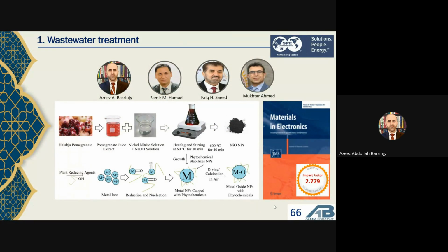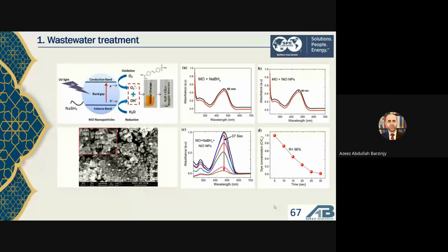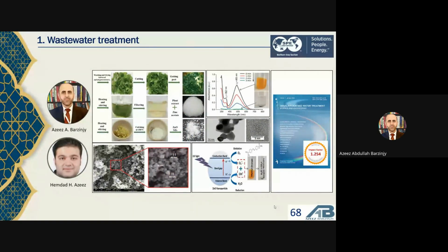And here we utilized homemade Halabja pomegranate in order to produce nickel oxide nanoparticles, again for dye degradation. But in this process, we could decrease the time of the degradation from 60 minutes to only 37 seconds by using the green synthesized nanoparticles. And we also utilized different types of plant extract in order to produce zinc oxide nanoparticles, and also utilized these nanoparticles for dye degradation.